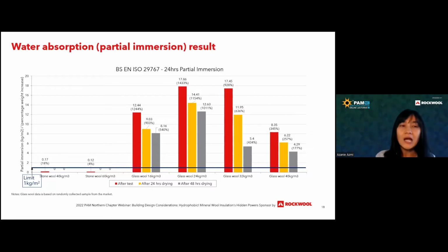We not just want to see how much water intake there is after the test. Remember, the test is actually 24-hour immersion, but we also want to see the performance if we let the sample dry at room temperature, whether the weight becomes lesser over a certain duration of time. For this test, we test the weight again at 24 hours and 48 hours. You see here the y-axis is in kg per meter square, and roughly what kg per meter square means is how much percentage weight increase. If you look here at Stonewool insulation, when we finish the test, it's around 0.17, roughly 18% of increase.